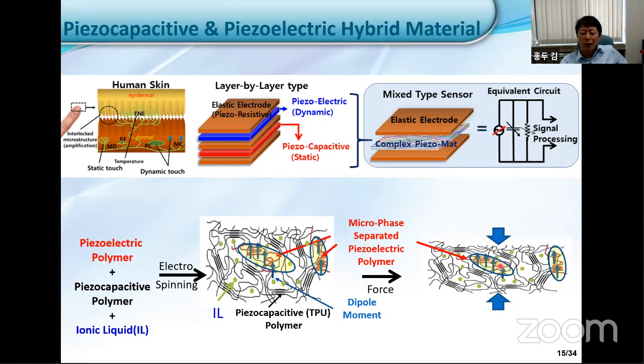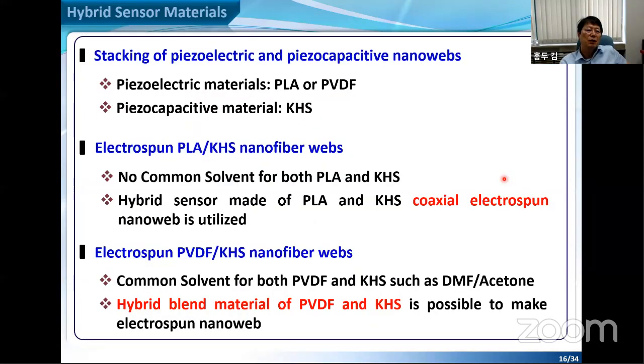So if we can design it very well, then we can measure both the piezocapacitive and the piezoelectric signal, as you see here, using this kind of circuit. From this idea, we can try different kinds of systems. The first is to just make the nanoweb and mechanically stack them together. This is the easy way. The second method is to try PLA with the KHS system. But in this case, we cannot find a common solvent for both PLA and KHS.